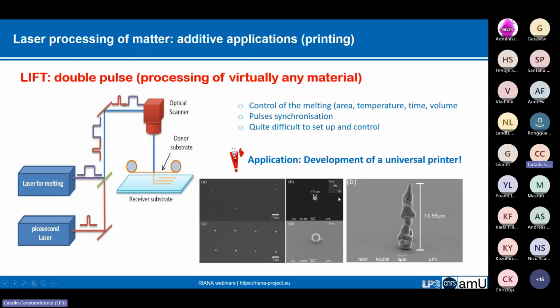The whole idea of double pulse lift is that it decouples melting and propulsion, and therefore allows virtually any material to be printed. So again, this is a step forward to a universal printer. My whole idea, for example, is to use it with high melting temperature materials like titanium carbide or tungsten or other similar materials. If we compare the droplet size, we can see here that we can print even below micron, so a few hundred nanometers. And furthermore, we can print by stacking them, so we can create pillars.